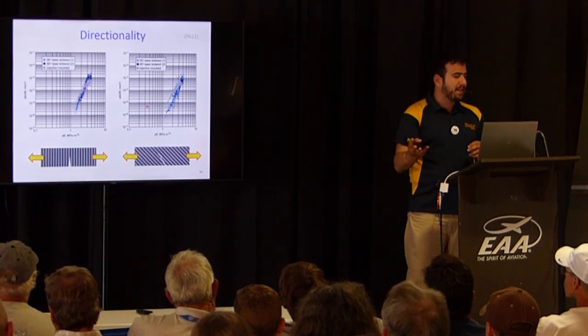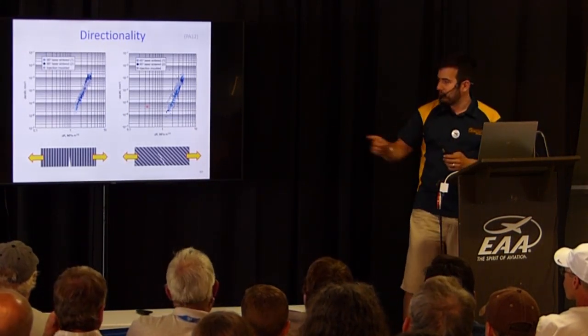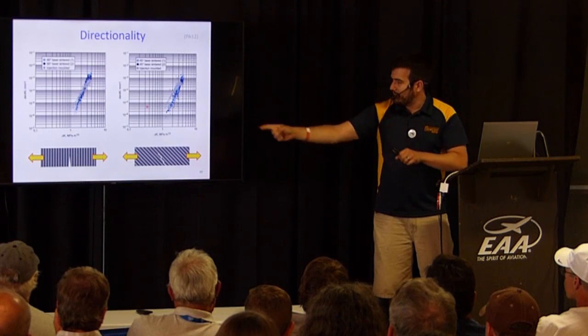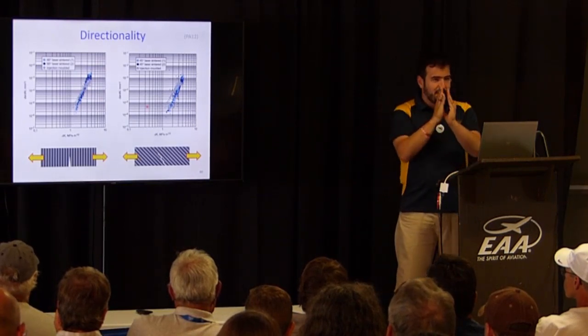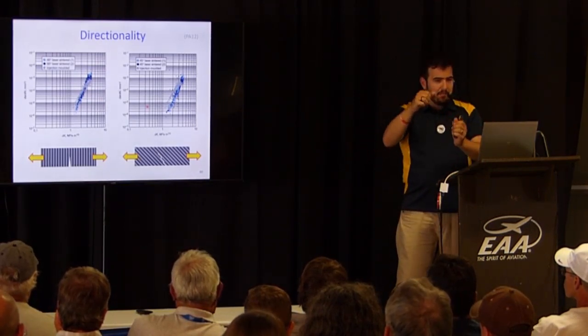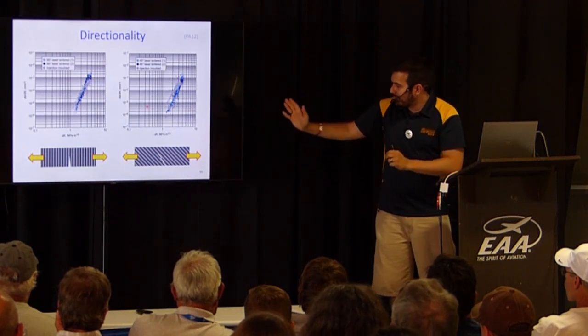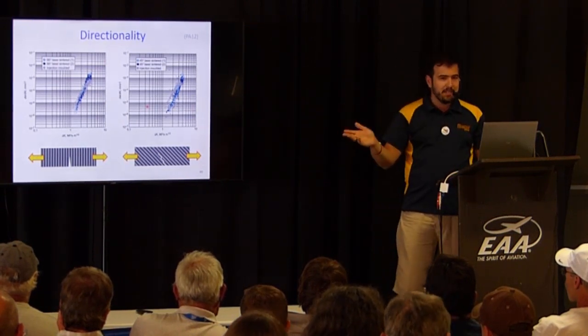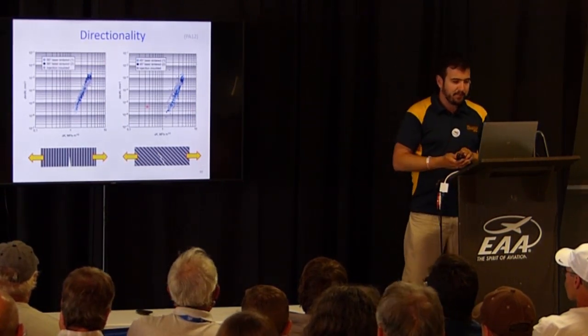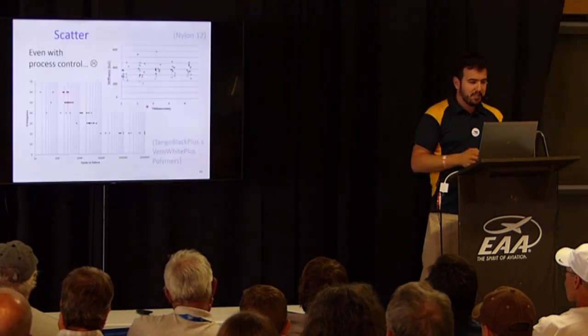And failure modes, cracking, are going to be different in different directions, right? If you're pulling something this way, perpendicular to the way it was printed, the 3D printed stuff is just going to split. But if it was 3D printed at an angle, then the fracture would progress and pull you a different way, a different mechanism. You get a different amount of strength, different fatigue properties.